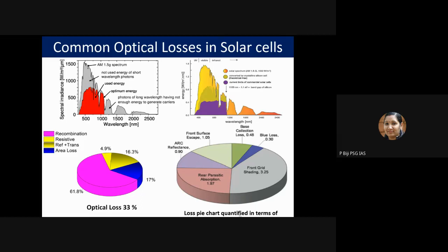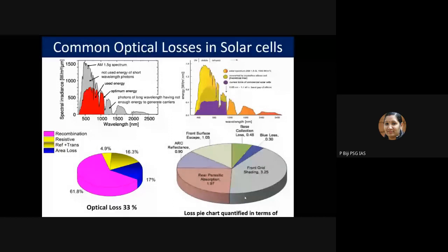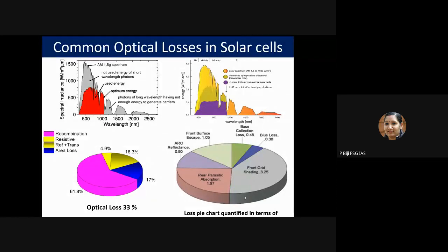Now the pie chart, which I have quantified in terms of the equivalent current density, is shown here. It shows that the front grid shading is a major phenomenon which has to be reduced, almost 3.25 milliamps per centimeter square. So the contribution is slightly higher compared to the other contributions.